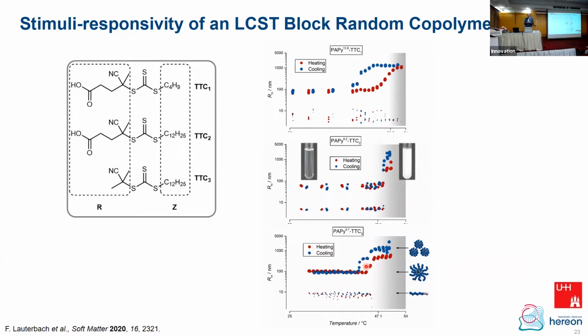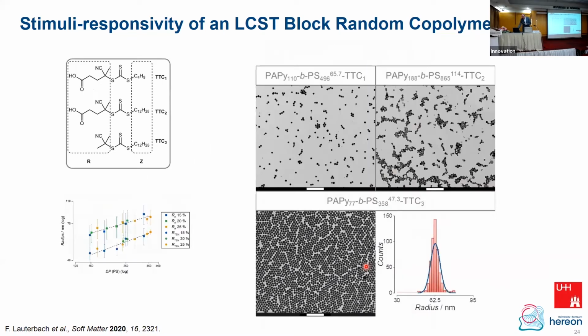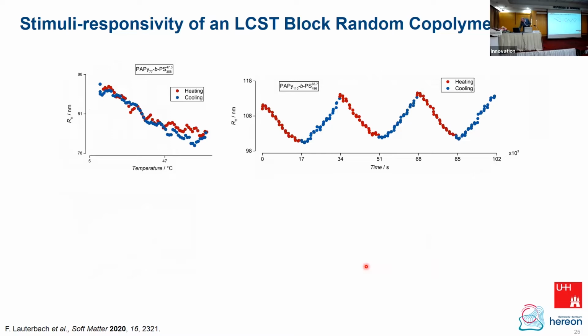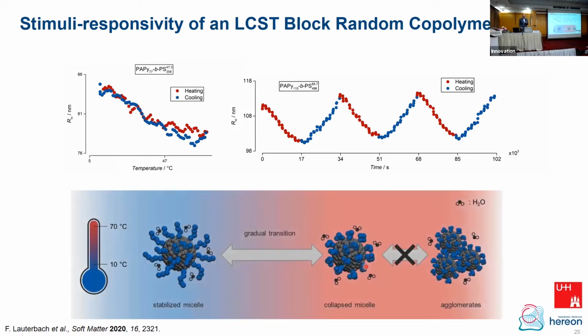You can aggregate and deaggregate, or rather, you get not aggregation but maybe swelling and deswelling. And here, these are just TEM images showing that these micelles are pretty well controlled. And the nice thing shown here is a fully reversible swelling and deswelling of the corona chains. You can heat the system, then they shrink because they are less soluble at a higher temperature, and then you can cool and they expand again. So the whole thing is somehow breathing with the temperature. This is the reversible down and up curve you see here for the hydrodynamic radius. And Felix did not observe irreversible aggregation in these systems.